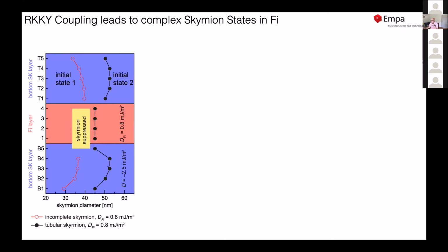And you see here that the skyrmion radius, the average radius, is considerably larger than if you have only skyrmions in the top and bottom layer. And the skyrmion radius in the ferrimagnet is somewhat smaller than here in the ferromagnetic layers. And remember, at this interface, through the strong coupling through the platinum, we get frustration. So this skyrmion is actually a Bloch skyrmion, whereas these are clockwise Néel ones, and these are counterclockwise Néel skyrmions, and here we have again clockwise.